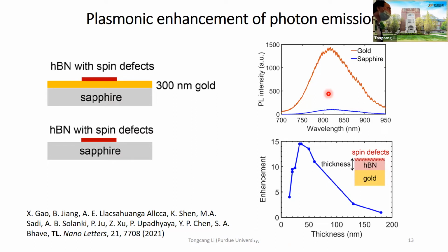I have a question about this plasmonic enhancement. Is my understanding correct that it only enhances the laser excitation? No, it does both. For laser excitation, you can think of it like a lens to focus light a little bit. But more important is the Purcell effect, which is basically you increase the quantum vacuum fluctuations there, so you speed up the decay. So you indeed see a shorter lifetime of the defects. Right. In general, if you put a single emitter or quantum dot there, the lifetime will be much shorter. But in this particular material, the decay is dominated by non-radiative decay, so you see a change of the lifetime, but not dramatic. I see. So the main effect is that the cavity plasmonic enhances quantum vacuum fluctuations, so that you speed up the spontaneous decay.